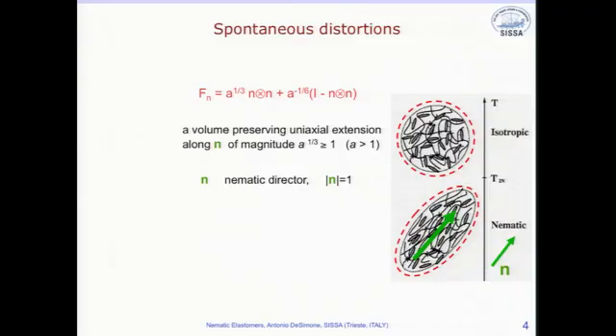So if we model the system as being incompressible, as it is standard for rubbers, the spontaneous distortion as well will be incompressible. There is a direction of alignment. That's the n direction. It's the only privileged direction. All the directions perpendicular to it are equivalent. There is a stretch in the direction of alignment. So the amount of stretch in the direction of alignment plus the constraint that the determinant of the deformation will be 1 to preserve volume determines everything. And so you know what is the spontaneous deformation.